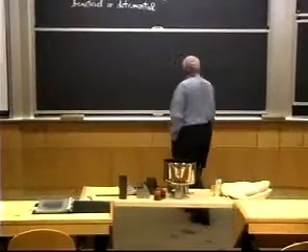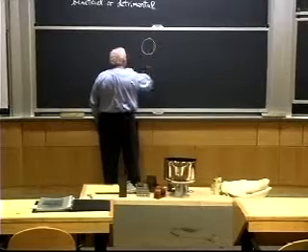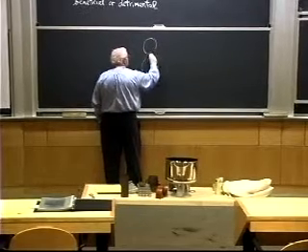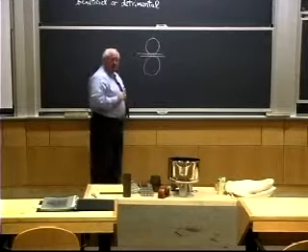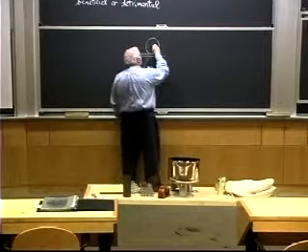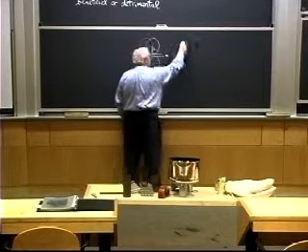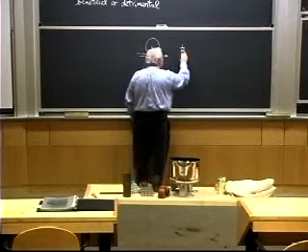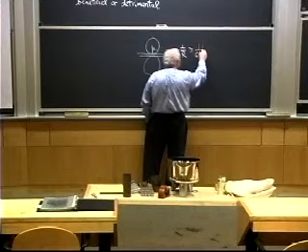It turns out that if you just try to roll a piece of material in a rolling mill, the thinnest that you can get is about, if this is the roll radius R and this is the thickness T, T over R is going to be greater than 1 over 500.